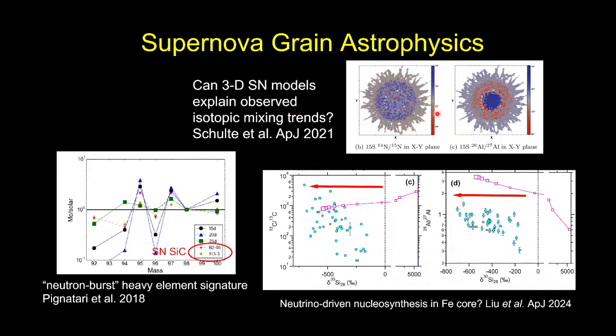There are recent results with 3D supernova modeling that's starting to get much more realistic and closer to the point where we can start directly comparing the models to what we find in the grains. From a nucleosynthesis point of view, we see interesting nucleosynthetic signatures that in some cases were not predicted or not noticed in predictions by supernova models before. But when you go back and look in detail, someone's done a computer model to calculate the nucleosynthesis in each layer, and it's like, oh wow, the molybdenum in a silicon carbide grain has this weird signature of these peaks in these isotopes, and discovered, oh, that's in this shell of a supernova model. No one noticed it before, so it's kind of cool.